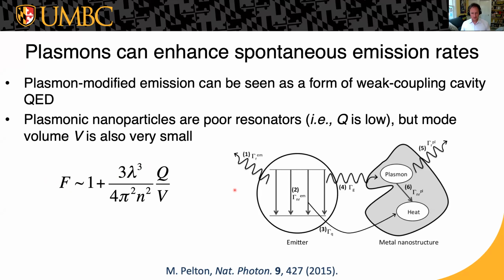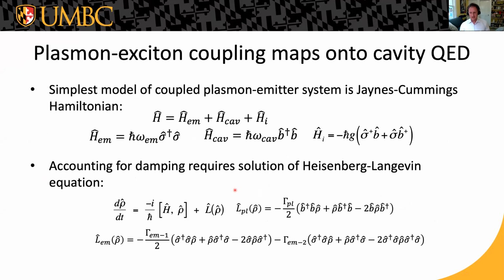So that did lead to the idea that these systems could also be used for strong coupling cavity QED, for formation of polaritons, hybrid plasmon-exciton modes or plasmon-emitter modes in these systems. And there really is a formal mapping between the cavity QED and this plasmonic cavity QED. In the simplest model, the Jaynes-Cummings Hamiltonian that's used for cavity QED, where you couple a two-level system to photons in the single mode of a cavity, you can replace the bosonic field of those photons with the bosonic field of the plasmons inside the cavity.